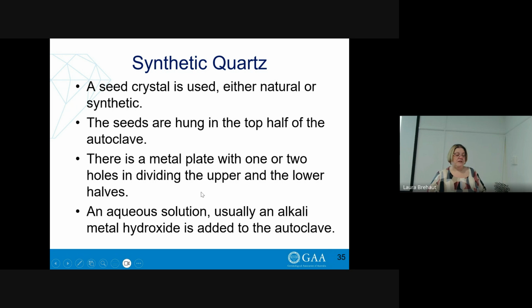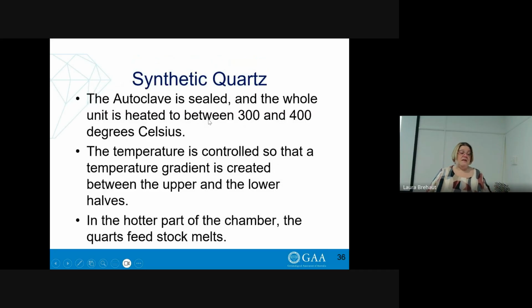A small metal plate with one or two holes in, dividing the upper and the lower halves, allows the nutrient to travel through. And the aqueous solution is usually an alkali metal hydroxide, which is added to the autoclave. The autoclave is sealed and the whole thing is heated to between 300 and 400 degrees Celsius. It must be less than 570 degrees because they don't want to induce any twinning in the crystals.